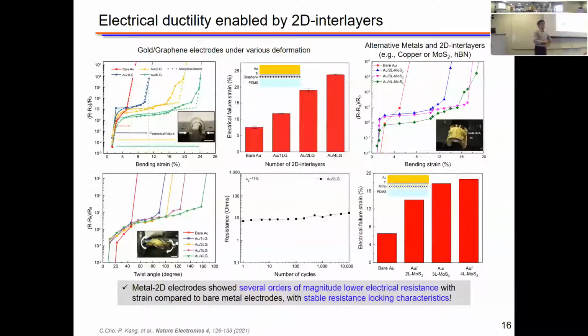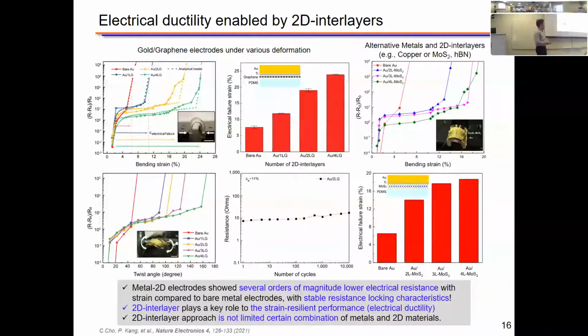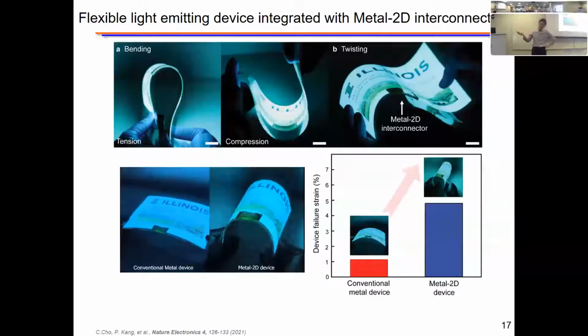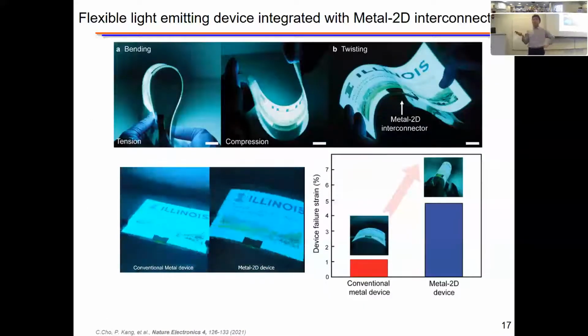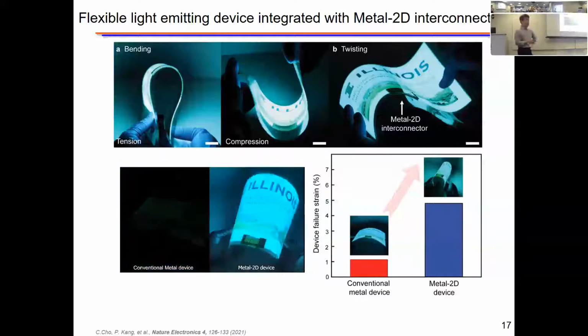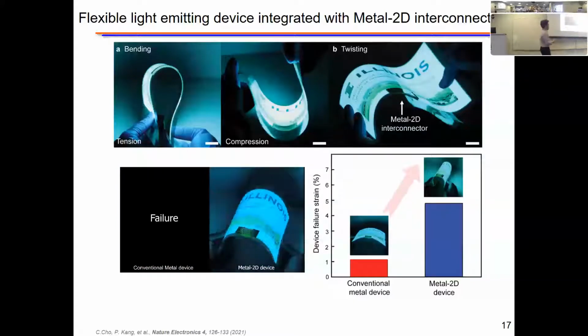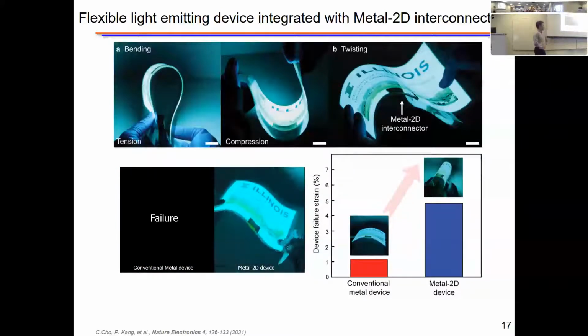We not only tested with graphene, but also alternative layers like MoS2 or hexagonal boron nitride, which is an insulator. So this confirmed that the 2D interlayer plays a key role in inducing this phenomenon regardless of its conductivity. And it's also not limited to a certain combination of metal or 2D materials. So at the end, we demonstrated our general applicability by creating a flexible light emitting device and demonstrating the augmented durability under various deformations.